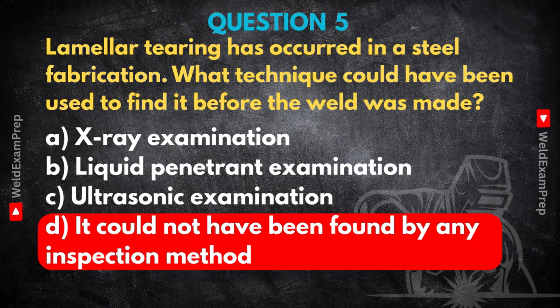That's the crucial shift in thinking from detection to prevention. Since you can't find the tear before it forms, you have to focus on stopping it from forming. Right. So first, scrutinize the material specification. Does the steel have guaranteed Z direction properties? That's a big one. It means it's tested for through thickness ductility. Okay, looking for Z-grade steel sometimes. Exactly, or similar designations. Also, check the material certs for things like sulfur content. High sulfur makes it much more susceptible. Got it. Material first. What else?